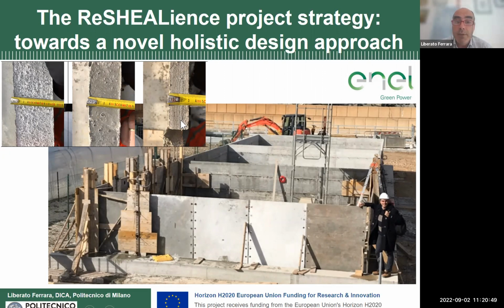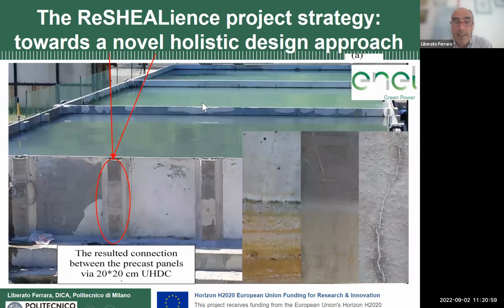And with this concept, you can see that the thickness of the slabs that we used for the walls of our basin was just 3 centimeters. And it worked perfectly well. You can see here the first load test that we made on the structure, filling them. Each of these tank compartments contains 50 cubic meters of water. You can see no signs of water leakage through the joints, but most of all, if you look at this picture on the bottom right of your slide, you can see the first rectangle is the ordinary reinforced concrete after